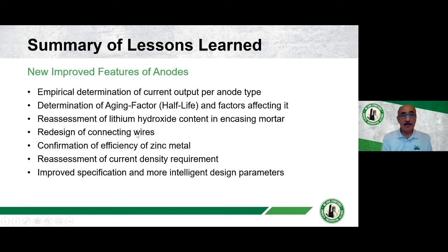We also redesigned the connecting wires. There's 2 reasons for that. The main reason was that it became easier for installing purposes to have a single wire going through rather than 2 sets of wires. It's a lot shorter in reality to install one with just the 2 wires. But there was also a slight problem we occasionally saw where the 2 wires were touching each other in the zinc core. There was an interstitial gap, if you like, and some lithium hydroxide solution could penetrate through that gap and start corroding the zinc from the inside. There's no way that can happen now because it's a single wire and it's totally encased in the zinc metal.